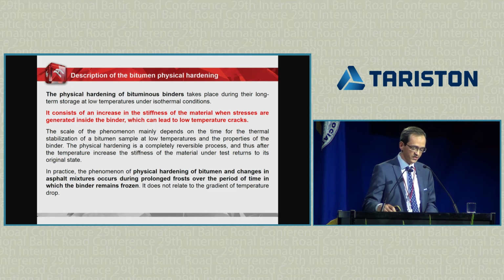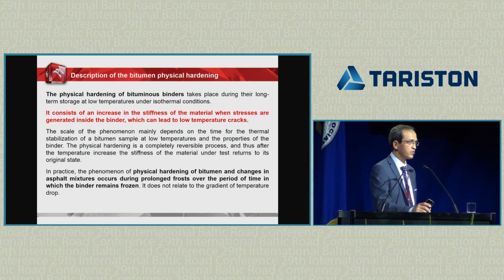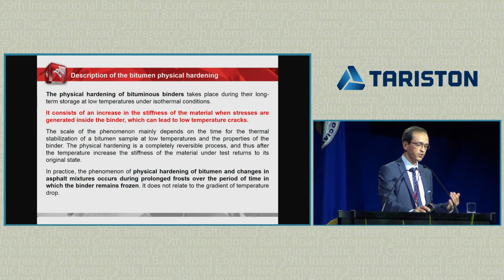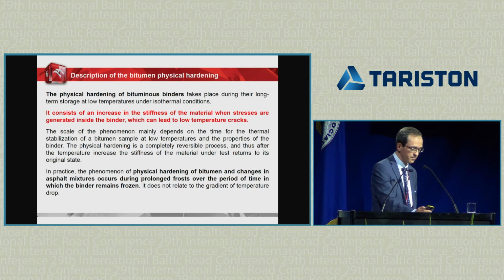What we think about physical hardening is that it is a phenomenon which takes place during long-term storage at low temperatures under isothermal conditions. We cannot join it with a fast dropping of temperature, but we should think about it as a state when the low temperature is steady and very low during a very long period. During this period, we can observe an increase in the stiffness of the bituminous material, and stresses are generated inside the binder, and then it could lead to thermal cracking.